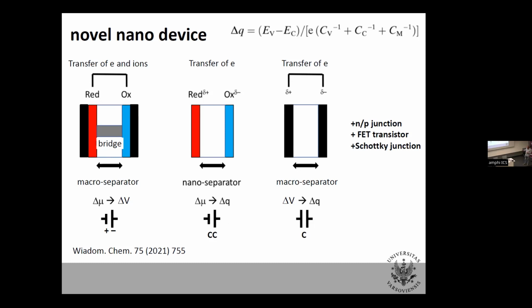But if you now use your electrochemical cell, whatever battery you have, and you rip out all the electrolyte, you are left with this. What is it? It's a totally spoiled battery. It will not work unless this separation is in the nanoscale. Then you have a chemical capacitor. And now the difference of chemical potentials can be changed to charge separation, depending on the distance. This device is good not for energy storage. It does not generate any electric voltage. It does not permit you to recover the charge stored. It's good for nothing except one thing.